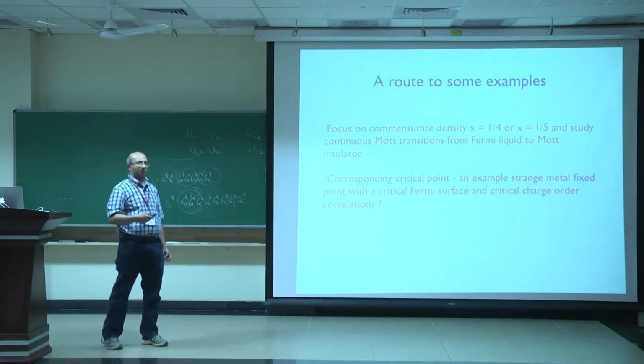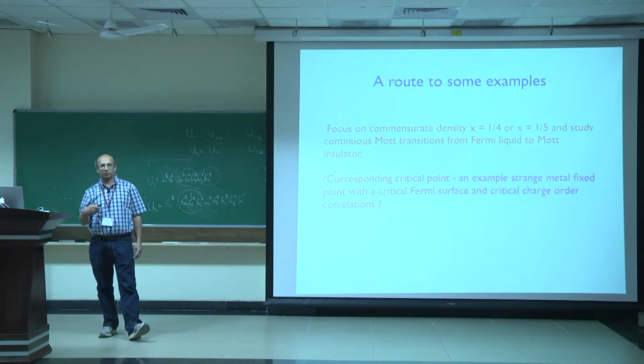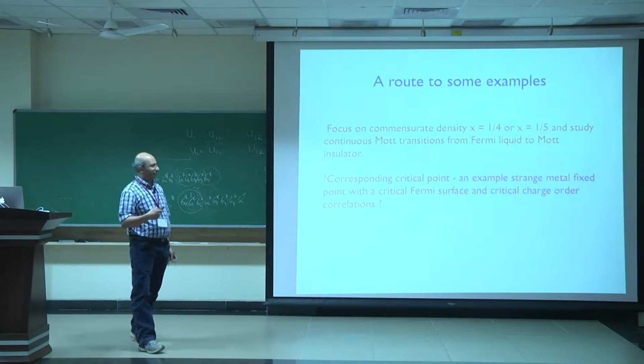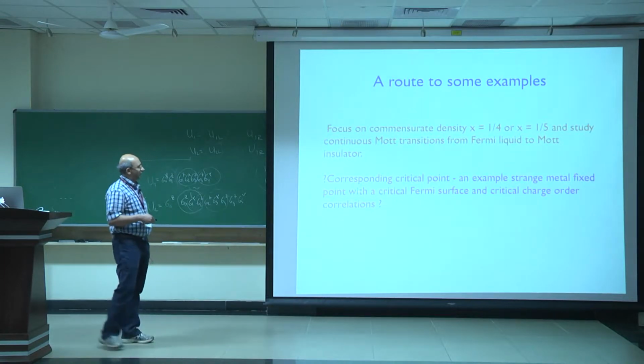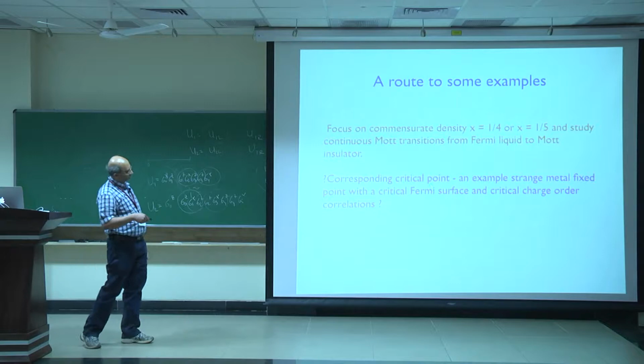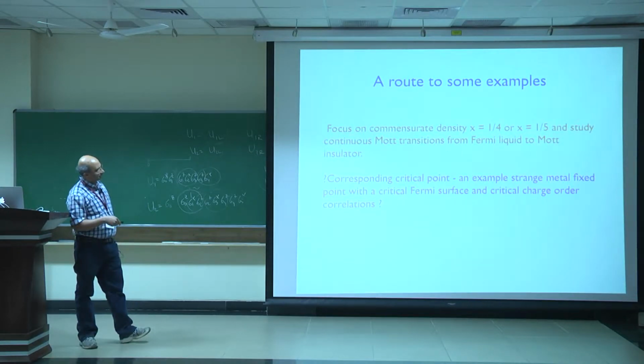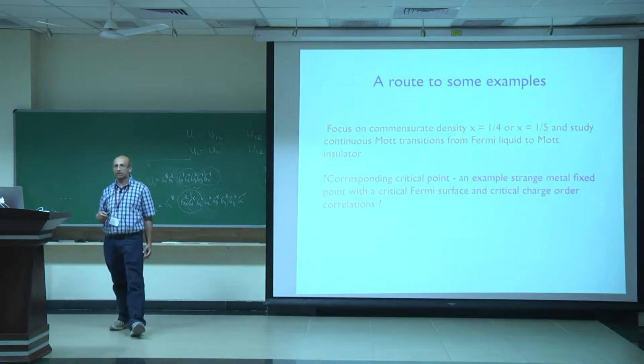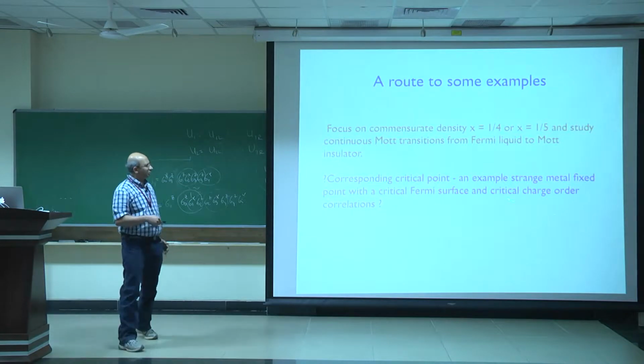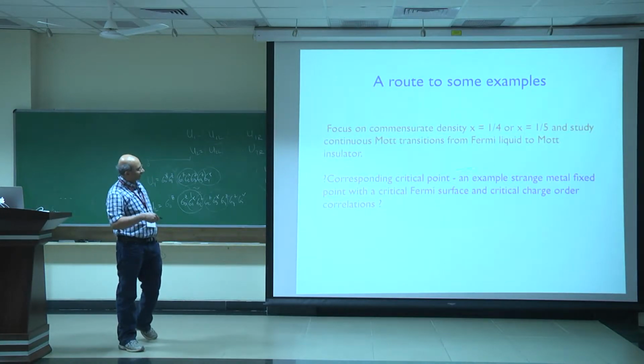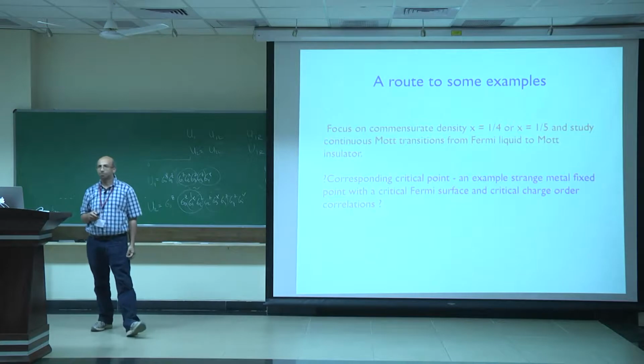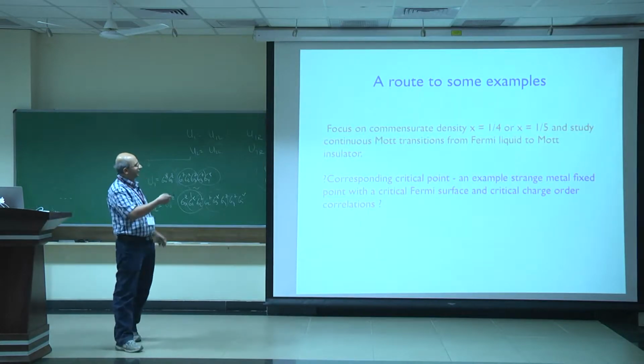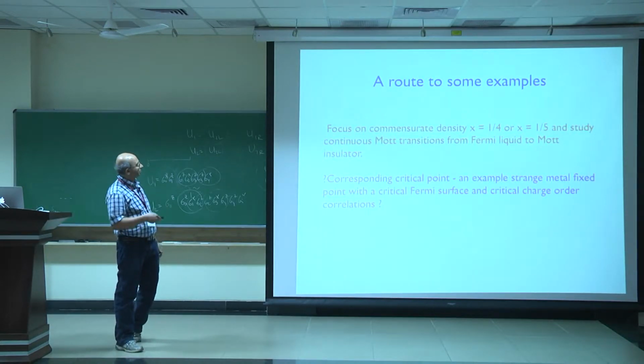If one could describe such a continuous phase transition, then the corresponding critical fixed point one might expect will be a strange metal with what one may call a critical Fermi surface, where there's a Fermi surface but no Landau quasi-particles, and quite naturally you might expect that it would coexist with critical charge order correlations. Okay? So let's see whether this gives an example or not.